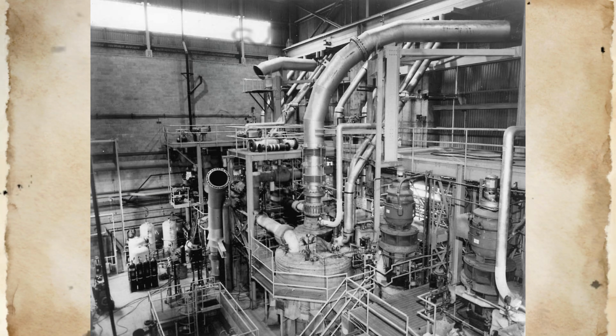At 3:09 p.m., the situation escalated from an operational challenge to a declared radiological emergency when radiation monitors in the building ventilation system detected airborne radioactivity above normal background levels. The radiation alarm provided definitive confirmation that radioactive material had been released from the reactor system, indicating that fuel damage had occurred and that the integrity of fuel pin cladding had been compromised. The detection of airborne activity meant that volatile fission products were being released from damaged fuel and transported through the reactor's cover gas system to the building atmosphere.